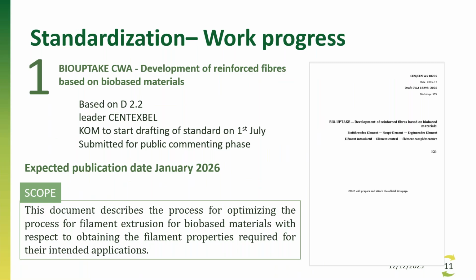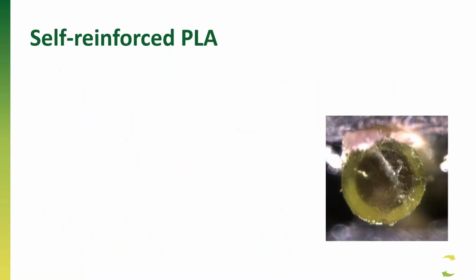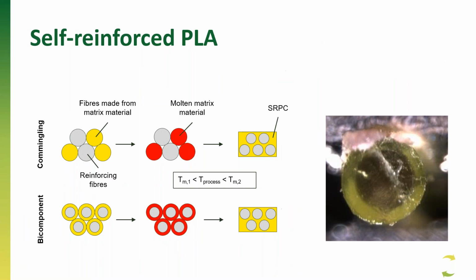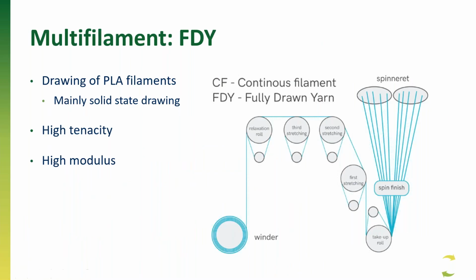For the first and second demonstrator, we use these fibers to create the organo sheets, and these fibers are bio-based materials. So we are doing here self-reinforced PLA, where we use a low melting and a high melting PLA grade together. They will be incorporated together, and the high melting grade will really form the reinforcement of the composite, while the low melting grade will form the matrix material. There are 2 ways to do this, but I will not go too technical into this process.